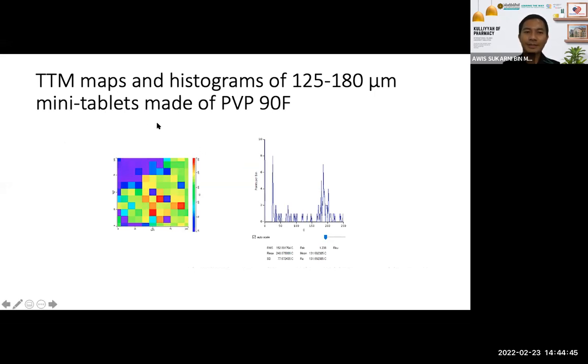And this one is the result from the mini tablet of polyvinylpyrrolidone 90F, PVP 90F. It showed the same pattern as the HPMC just now. You can see there are a lot of different transition temperatures, even though it's only one polymer. If you look at the histogram, there are a few points between 225 and 250. Basically, they detect a lot of different transition temperatures in this range.